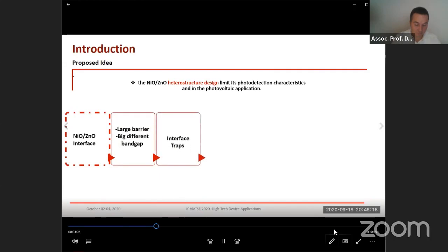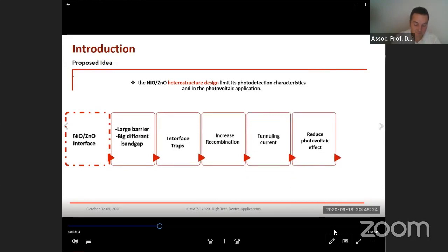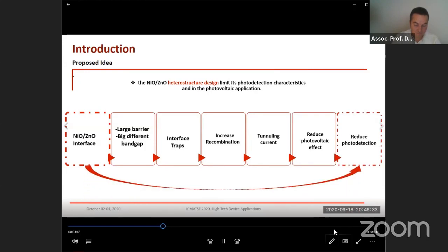beside interface traps. The presence of these traps increases the interface recombination and tunneling current, which gives a low photovoltaic effect, which means low photodetection. In short, there is a relation between the NiO/ZnO interface design and device performance. Our research began from here.